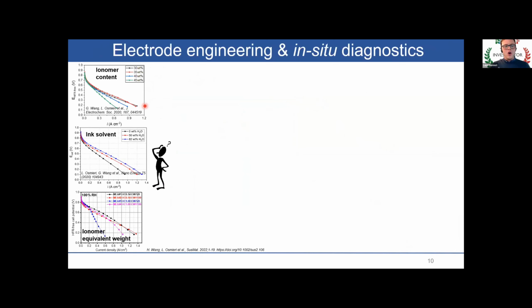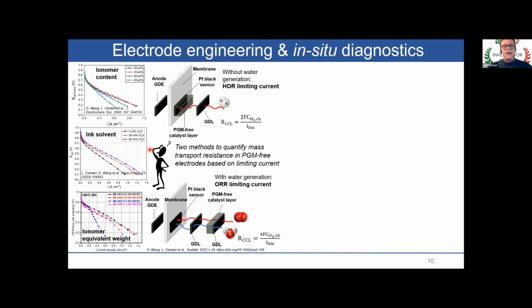Talking about electrode engineering more in detail, when we fabricate the electrode, we basically mix the catalyst powder with some ionomer and we disperse it into a solvent, forming an ink that gets deposited on various substrates in order to fabricate the electrode. So we have explored different fabrication parameters like the ionomer content, the ink solvent composition, and the ionomer equivalent weight, and found a big variation of performance depending on the operating condition. So we tried to develop a strategy to understand why these improvements were actually happening.